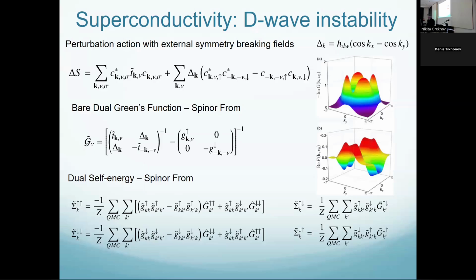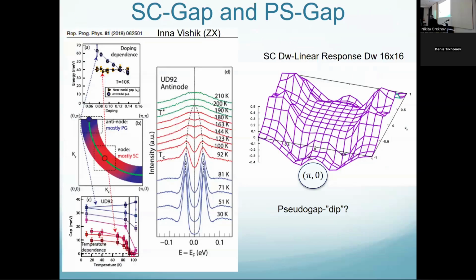But the maximum is not at the so-called nodal point. And if you compare with experiments, this is our Gorkov Green function, and the maximum is not at pi 0. And if you look at this review article on cuprate superconductivity, on the Fermi surface they see two different gaps. Here and here, exactly at these two points, the gap is not superconducting. They say that it's a pseudogap. It's a big gap. It stays with temperature. It even increases. And the superconducting gap is somewhere in between. Here it is 0 by symmetry because it's a nodal D wave, but the maximum is not here, somewhere here. And only this superconducting gap reduces as a function of temperature, and vanishes at 100 Kelvin. And we can start to see this physics.